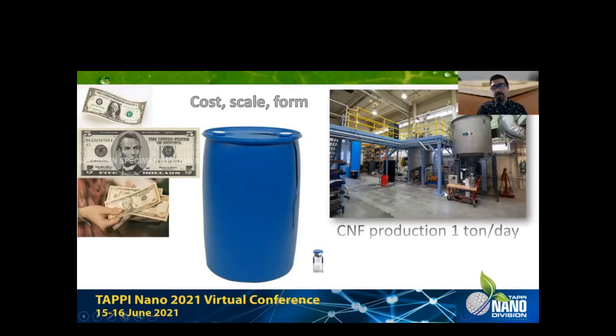On the right, you have a picture of our cellulose nanofibril production line at the scale of 1 ton on dry basis a day. And then I also have a picture here of our spray drying pilot scale production line, which basically is on the same scale, pilot scale, but it can only produce 1 kilogram a day of dry nanocellulose. So we can produce a ton a day, but you can only dry about a kilogram a day.